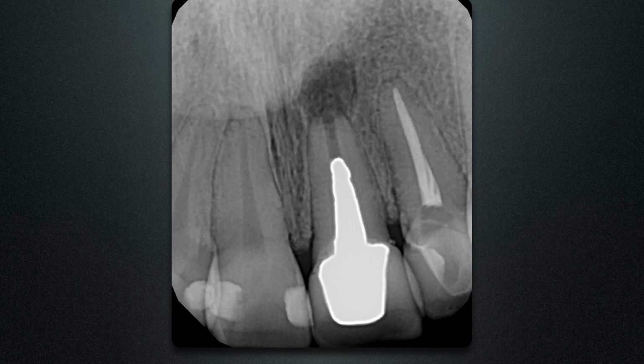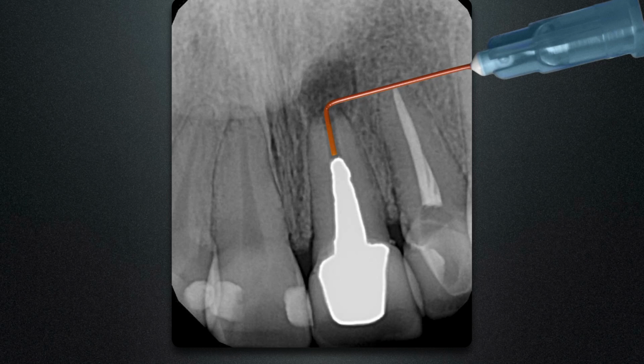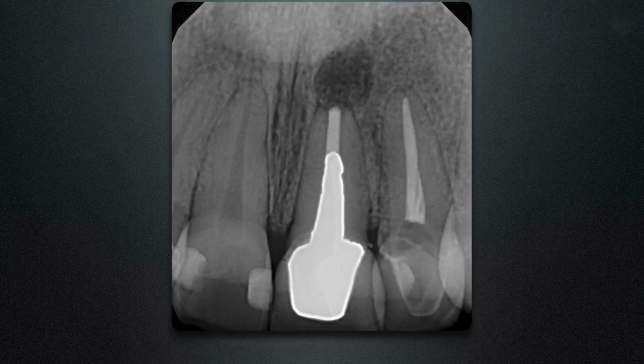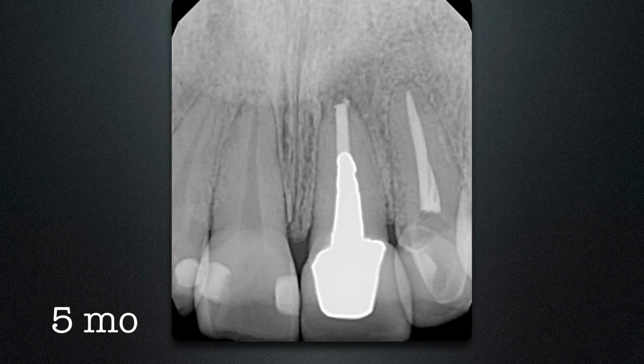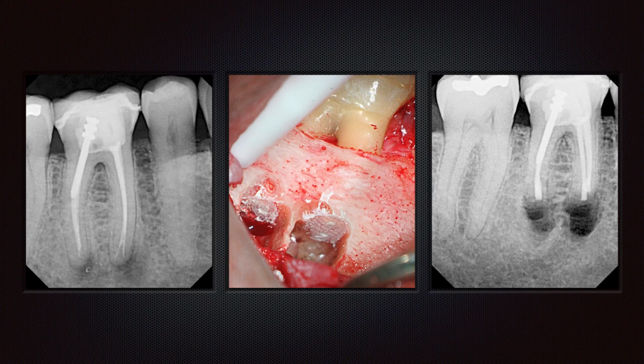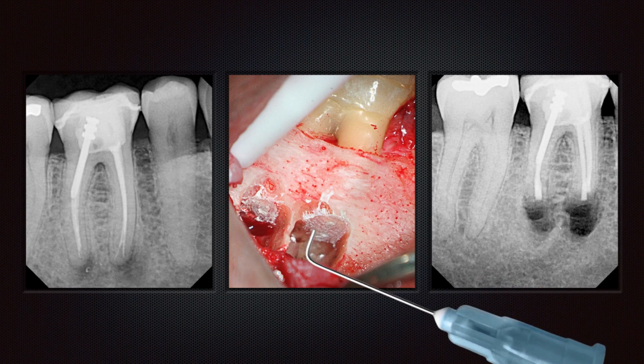Also, as you can see, you can use this tip now and remove all the gutta percha all the way to a post in an anterior tooth, for example, and then fill all the way back up and fill the root canal space all the way from the post up using these longer tips. So that's a tremendous amount of benefit, and here's a case that you can see that has healed beautifully in follow-up. And also in molars, these tips allow you to have the bendability to basically shape it to be exactly the right angle and the right position, so that you can go in there and, especially in these lower molars, quickly retrofill your cases, which has been really the challenge in the past.